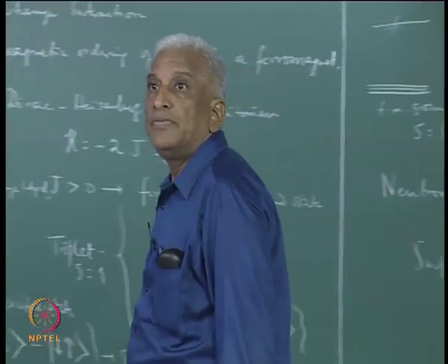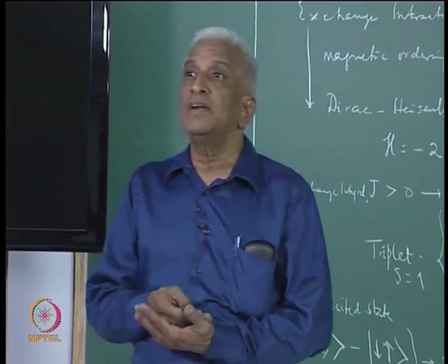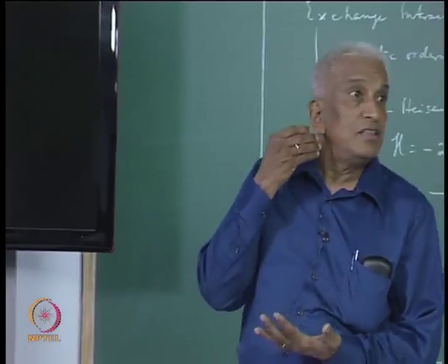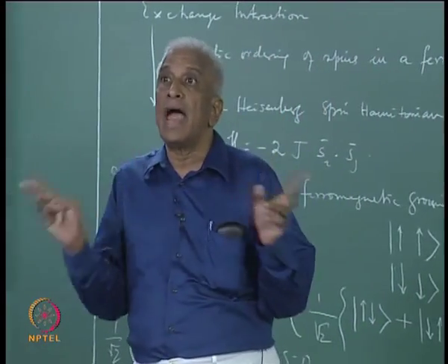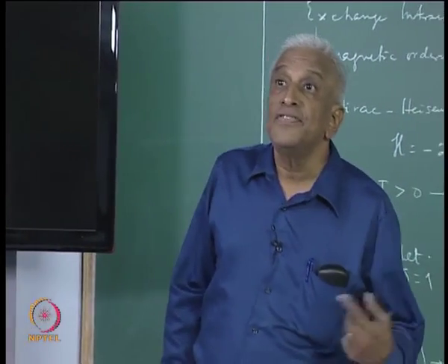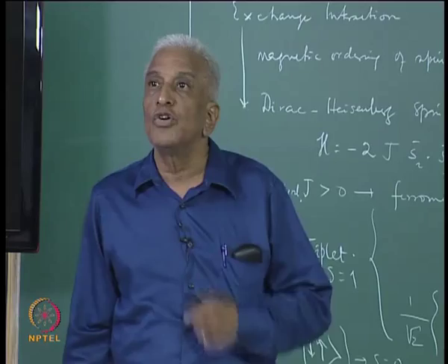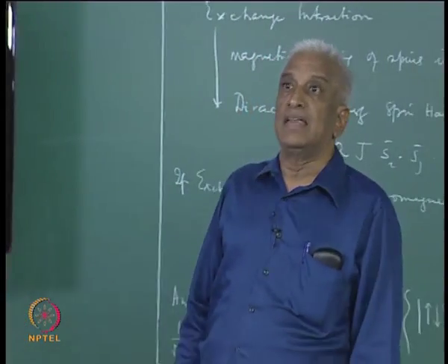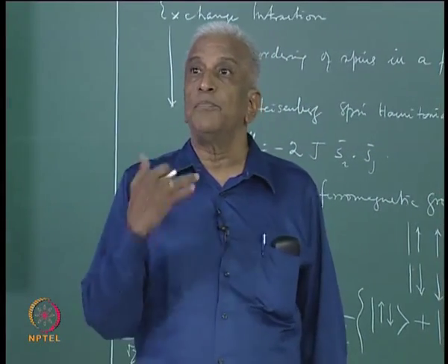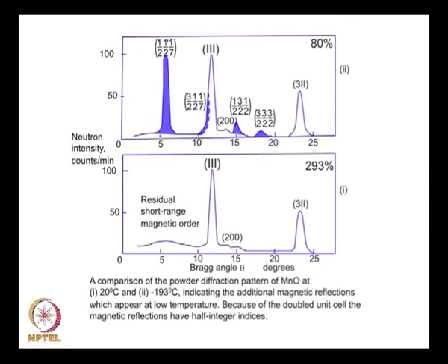So, this clearly shows that the ions occupying the body corners and the ions occupying the body center are anti-parallel. Therefore, there is an antiferromagnetic alignment, and this causes a non-zero Bragg reflection from the 100 plane. So, this extra line, which is not normally present above the Néel temperature, will start appearing below the Néel temperature. So, one can determine the Néel temperature also in this way.